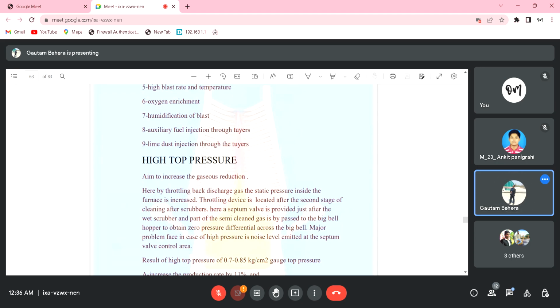FeO.SiO2.Al2O3, right? It is a ternary compound, so it has a low melting point. So this slag forms earlier, first. Then the second kind of slag is called Bosch slag because it is formed at the Bosch region. So primary slag is actually acidic in nature, but Bosch slag is basic, right?